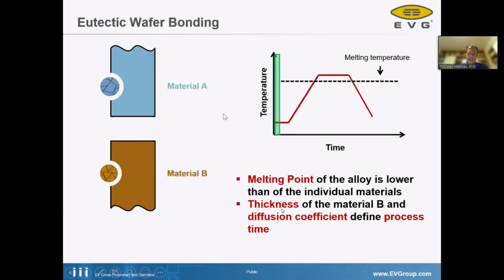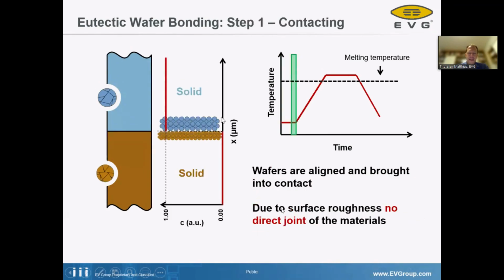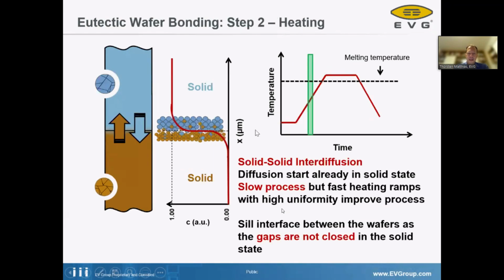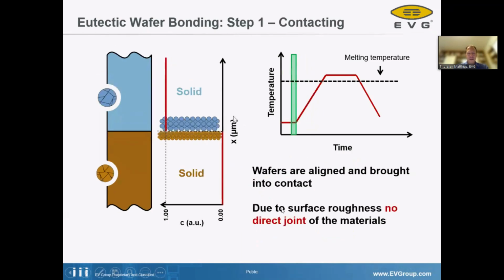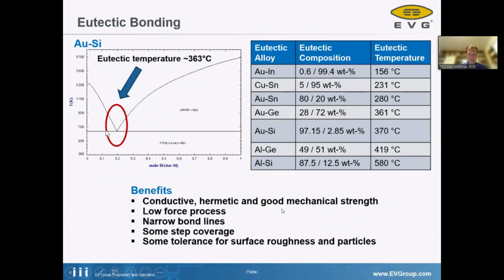So here we see again the same kind of cartoon style demonstration for the bonding process. Let's assume I have a binary alloy, material A, material B. I bring the two materials into contact. At this point, I have two solid interfaces. But then during the heat up, I already see some metal ion diffusion. And what happens is, as I have this metal ion diffusion, let's jump back, I'm actually moving in my phase diagram from both sides towards a stoichiometric composition where I have the lower